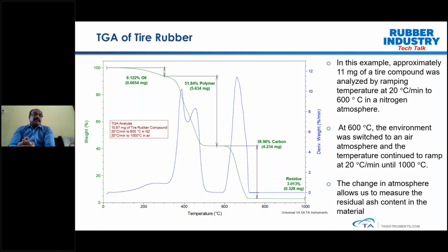So what we observe is, on the x-axis is the temperature, on the y-axis on the left hand side is the weight percentage, and then the y2 axis, on the right hand side, is the derivative weight. As we heat the sample, we start from 100% and the sample starts decomposing. As you can see, at a lower temperature, the high volatile oil components start coming out, which accounts for 6.12% of weight change. As we heat further, we see the polymer decomposition, which accounts for almost 51.84%. At this point, the weight is again stabilized.